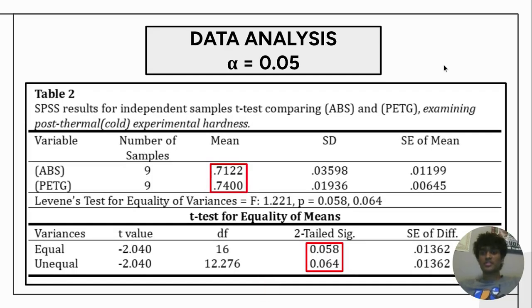In terms of the same thermal resistance test in the cold variant, the mean for ABS was 0.7122 and for PETG was 0.7400, and the p-values are 0.058 and 0.064, which is in fact above the alpha threshold of 0.05, indicating no statistical significance between these values, meaning that in terms of cold temperatures, no plastic was better suited than the other.